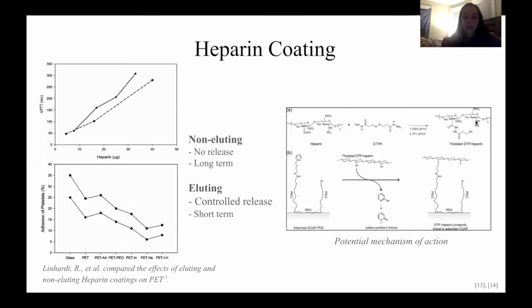On the left, you can see we considered two ways to incorporate a heparin coating onto the leaflet surfaces, either as an eluting or non-eluting coating. One study compared ionically and covalently bonded heparin coatings on a PET polymer. While the results showed a higher activated partial thromboplastin time for the ionic coating, researchers found increased bioactivity and reduced platelet adsorption in the covalently immobilized coating compared to the ionic coating.